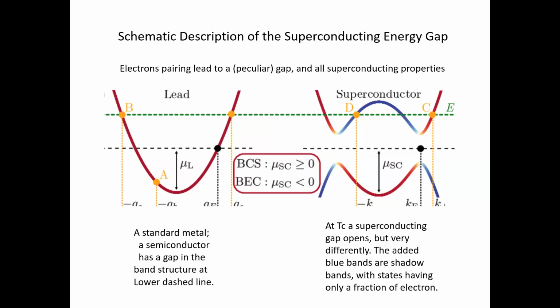And then there's this energy right here, which is called the Fermi energy, which is where everything in a metal happens. At very low temperature especially happens right around there. And don't pay any attention to this line up here. And in a semiconductor or an insulator, you don't have a continuous spectrum here. You have a gap. Forget about the blue for the moment. You have a gap. And what happens is this band gap opens up and achieves a maximum here and a minimum here. And this is the gap in an insulator or a semiconductor. In a superconductor, you have a gap like this, but it's very different. That much of it is the same.